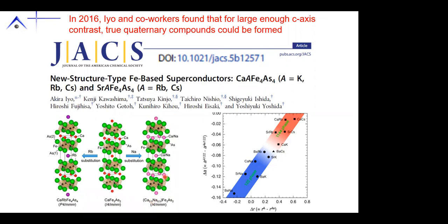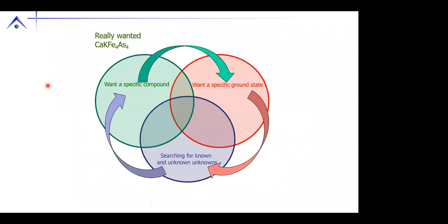On the other hand, if you have high enough contrast, in Iyo's paper they use the example of calcium and rubidium. Okay, then you can get a true quaternary where you have layers of rubidium, layers of calcium, layers of rubidium, layers of calcium. Okay, when we saw this discovery in polycrystalline form, we really wanted to make this compound master. So the first thing we wanted to do was see if we can make single crystals.